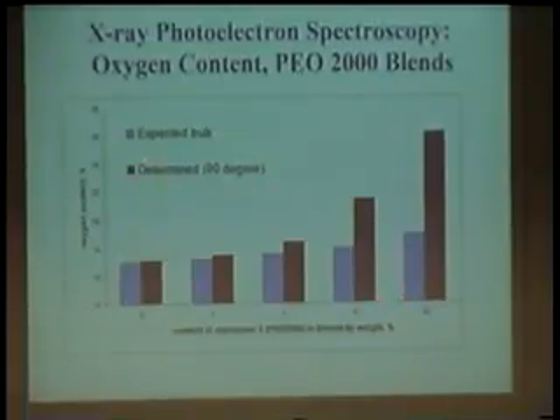If you look at the XPS data itself taken at 90 degree takeoff angle, you see that these pink bars are way above the blue bars, especially at the higher loadings, indicating an enrichment of PEO at the surface, as you would expect. And in fact, when you get to the 20% one, you see that the number is about 26 atom percent of oxygen, and that is exactly the same atom percent that you have in the copolymer itself. And that suggests that the surface here is completely covered by the copolymer at that composition, even in the high vacuum atmosphere of the XPS machine.